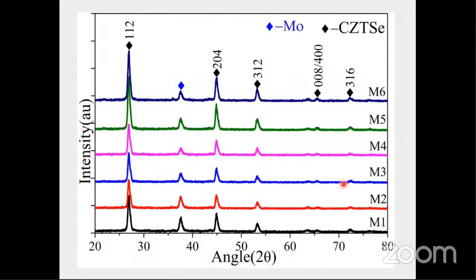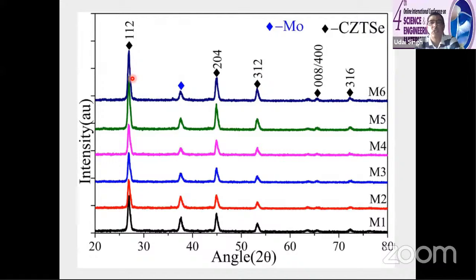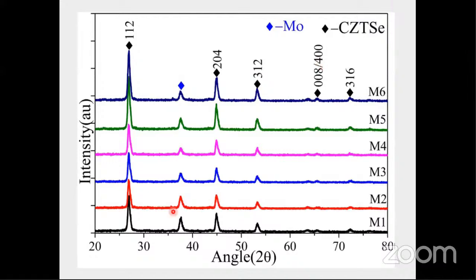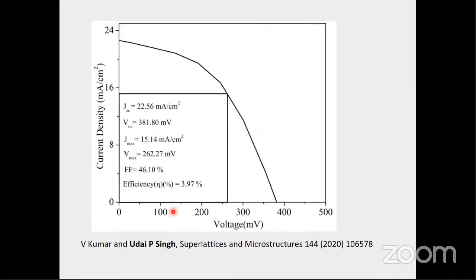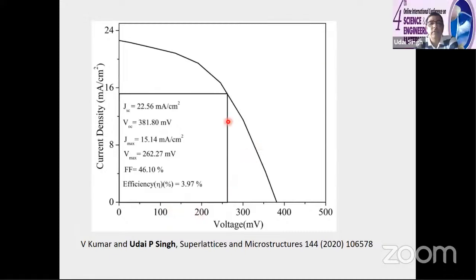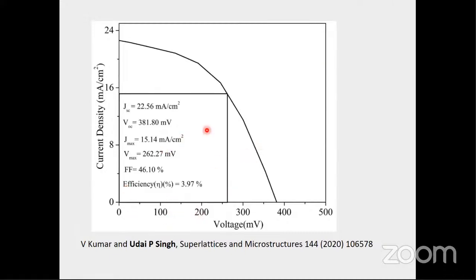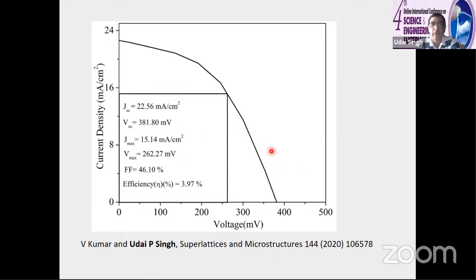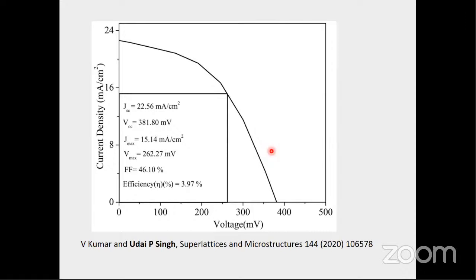We get basically all the CZTS peaks. No other binary phases are present there. So the highest efficiency we achieved is only 3.97%. This is on a small scale, which we published in Superlattices and Microstructures in 2020. So still a lot of work has to be done in this material.